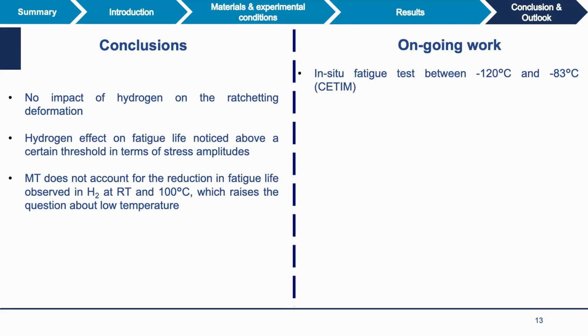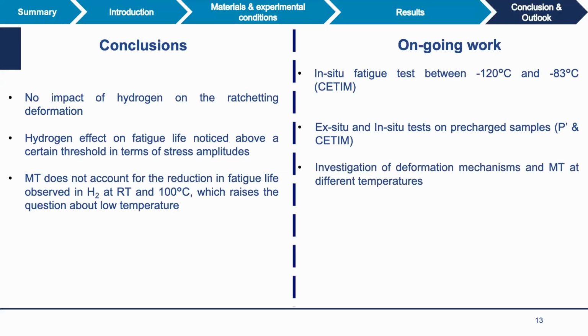We have some tests planned at lower temperatures in CETIM, and we will also perform some tests on pre-charged samples, and we will also investigate the deformation mechanisms and martensitic transformations at different temperatures using TEM and EBSD.